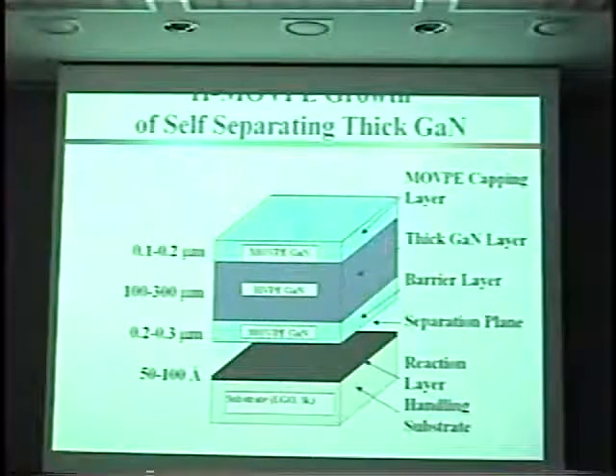The process we ended up with was one in which we took our handling substrate, and I'm talking about LGO at this point. We put this reaction layer, this buffer layer, this interfacial layer that we designed. It was the gallium lithium oxynitride. We grew a buffer layer or barrier layer using traditional MOCVD at about 850 degrees C. We then went into our thick growth during hydride VPE. Interestingly, when we grow hydride VPE, we become nitrogen terminated, whereas when we grow MOCVD, we're gallium terminated, so we get a polarity switch when we switch growth techniques.